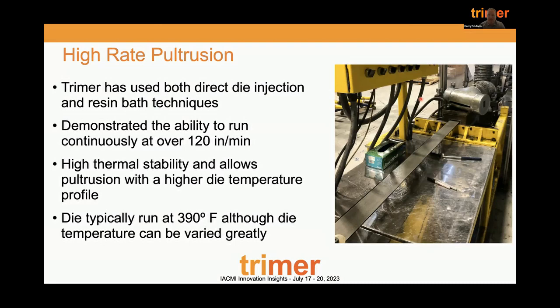I think the fastest you can typically pultrude, and what I've come to understand, is about 18 inches a minute for a phenolic, maybe a little less in many cases. And we're able to greatly exceed that while providing equal or better fire performance and significantly better mechanical performance. Really, that's a huge application space for us: fire resistant composite structures.